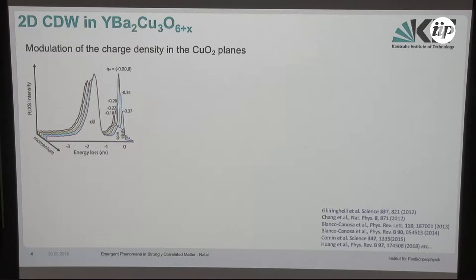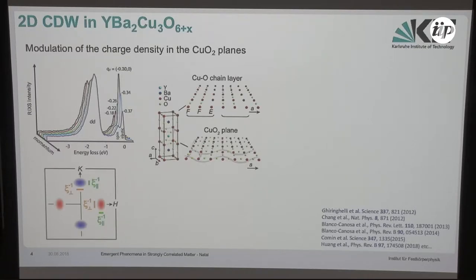So I start first with the charge density wave without the field, which historically was found after the one in high field, but we found it a bit by accident. This is resonant inelastic X-ray scattering, the spectroscopic method that we use to study the spin excitations. What we noticed is that the elastic line, which corresponds to zero energy loss, measured at different momentum transfer, had the maximum somewhere in the middle of the gamma-X direction. To make a long story short, if you translate that into a reciprocal space picture, you find that there are two sets of satellites with different correlation lengths that correspond to a supermodulation of the underlying lattice.